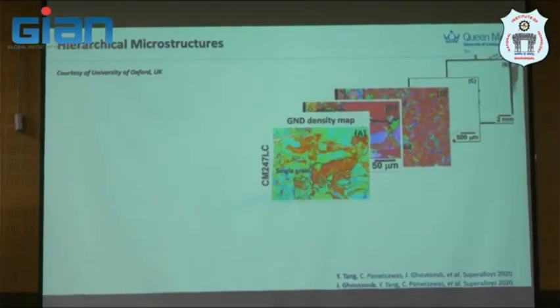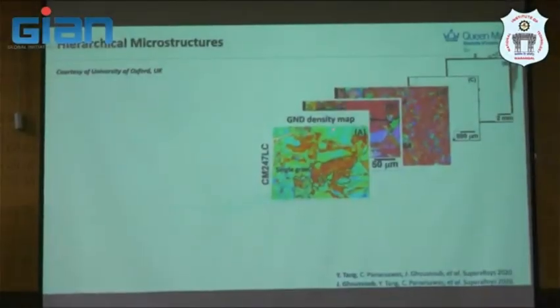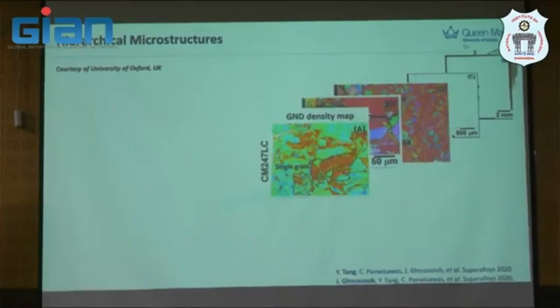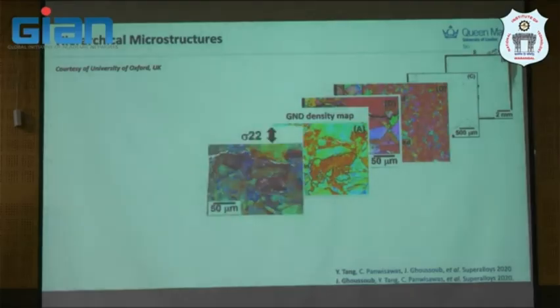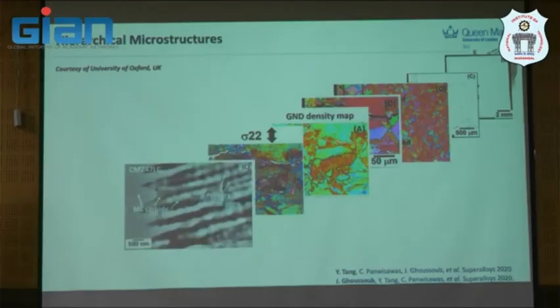But if you zoom in even more, using the high resolution EBSD, you get the map of this zone, and then you will see that in a single grain, there are hard and soft phases. So residual stress, type 1, type 2, type 3, can all be extracted from this kind of study. So there is a softer and stronger part in one grain. And if you look at the residual stress across the crack here, this is a profile, and this is quite heterogeneous. And then this may be related to the microstructure. Now I'm going down to nanometer scale.